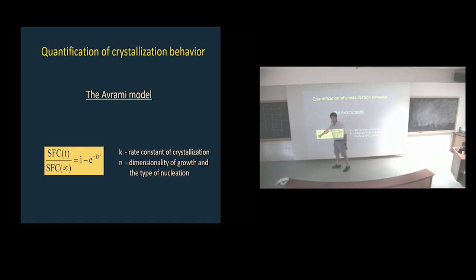We used the Avrami model, classic metals, and you have this, that's a sigmoidal. And it's not a bad model. It's actually based on theory at least, and not somebody's current purchase of a curve-fitting software, which happens a lot. It's like they have discovered the moon when you do a Gompertz equation. At least this is based on some theory. See, we have the solid fat content we can measure, and there's a rate constant k and a coefficient n. The coefficient n is the dimensionality of growth, and k is sort of some weird unit rate constant of crystallization.